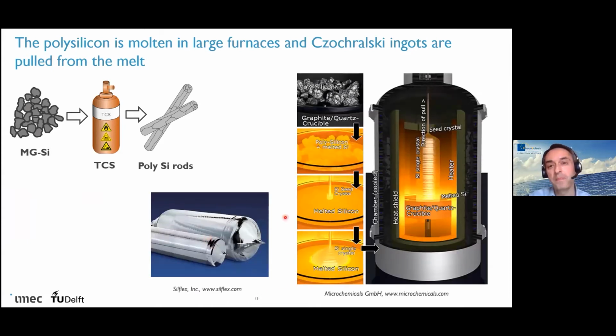Basically, what we do is we take a very large crucible, typically made from quartz or graphite, and we fill this large pot with all these polysilicon chunks. We put it in a very large furnace, we heat it up until temperatures above 1400 degrees, so that the silicon is really melting.